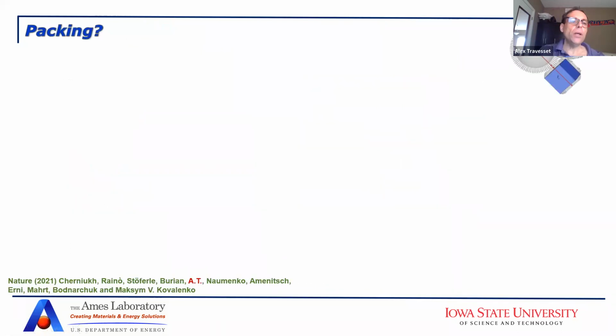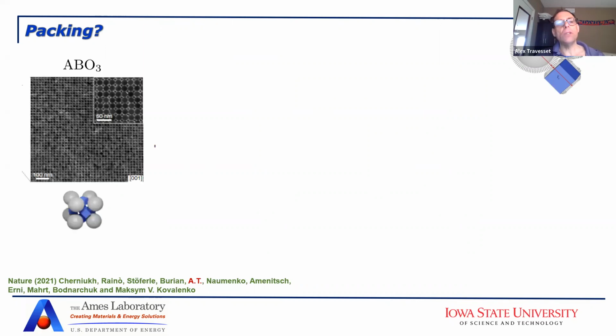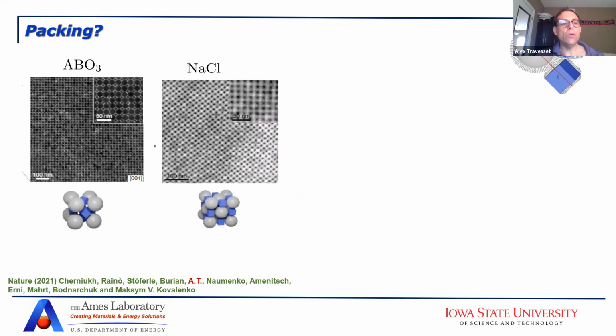So what we do here, as usual, we already know the rules. We first consider the hard sphere, and then we see in which situations you will have the presence of voids. And then based on that, we predict the packing fraction. And indeed, we concentrated, for example, on these two types of superlattices. For this type of superlattice, these are the structures. The ABO3-type has these cubes here, and there's another cube at the center, and they are tilted, rotated, and the sodium chloride is the type of sodium chloride that you expect.